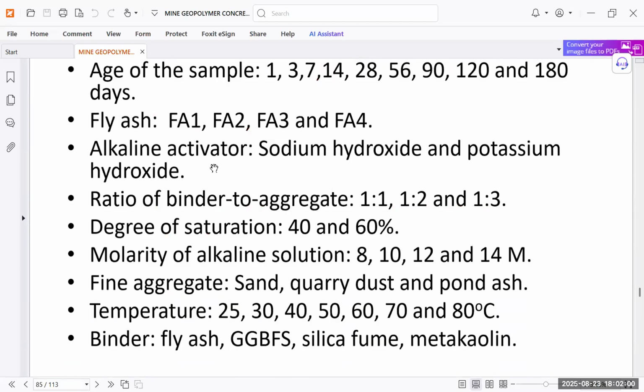The ratio of binder to aggregate in this case is 1:1, 1:2, 1:3. The degree of saturation is 40 and 60%. The molarity of the alkali solution we have changed from 8 molarity upward. For fine aggregate we are using sand, quarry dust, and pond ash. And the temperature we are maintaining is 25, 30, 40, 50, 60, 70, 80. And the binders we are using here are fly ash, GGBS, silica fume, metakaolin.